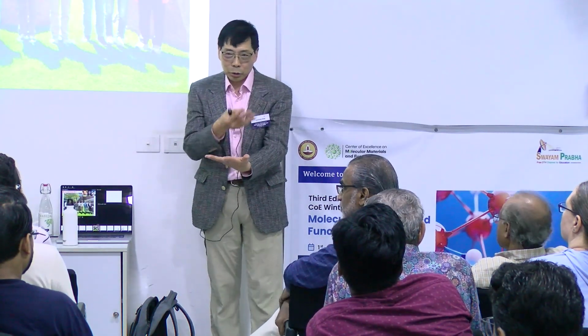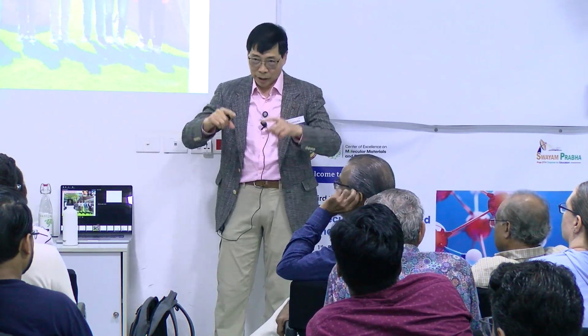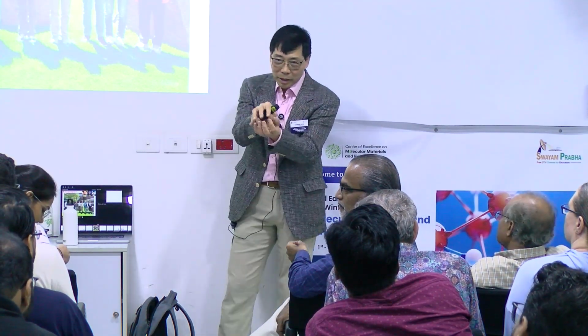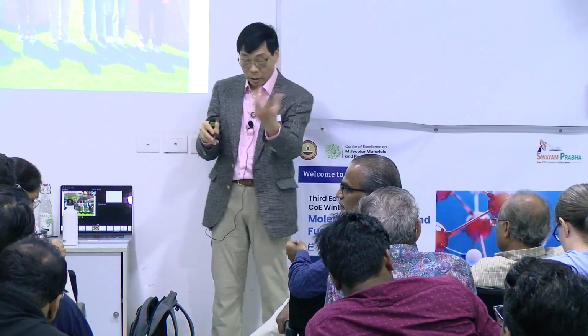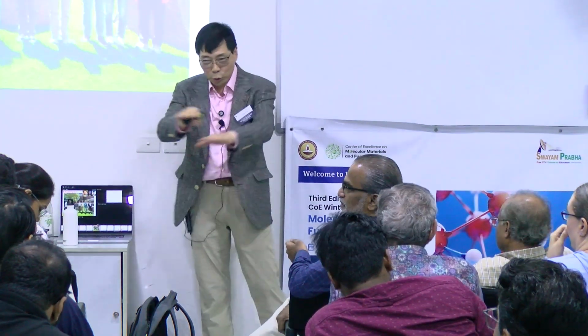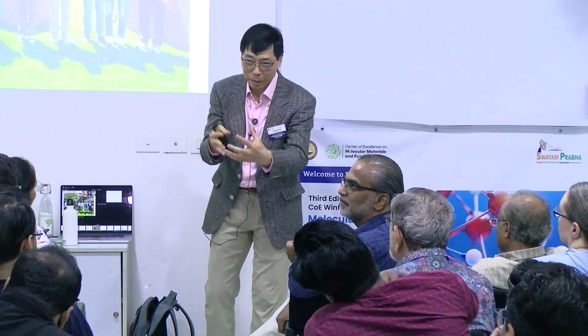So I think the 2D, the planar structure is the best way. Essentially, it boils down to electron sharing, electron delocalization. And in 3D, to form this cage structure is the best way to share electrons. In those cages, all electrons are shared. So I think in finite systems, the two-dimensional structure is the best way. Now, if you add hydrogen to terminate those dangling bonds, then they basically behave like a bulk, right?